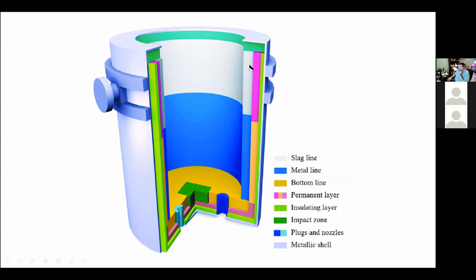It uses different types of refractory depending on whether the refractory is likely to contact steel or slag. You can see this area here is identified as the slag line, in the white here. In the bottom, you'll see that it's got several openings. This one is actually a porous refractory plug called a porous plug, and it's used to introduce gas into the ladle to stir it in order to get good mixing and homogeneity in the ladle. After we add alloys, it's very important to get them well mixed in so that it's homogeneous.